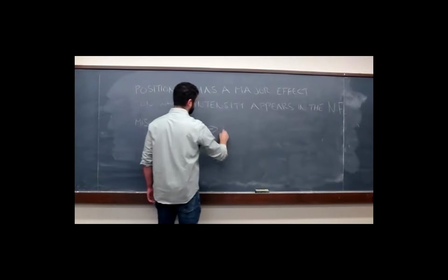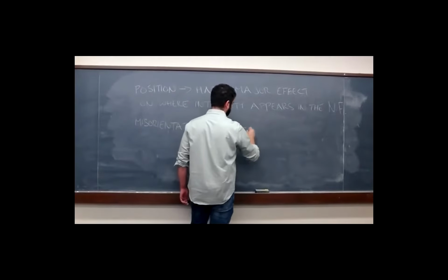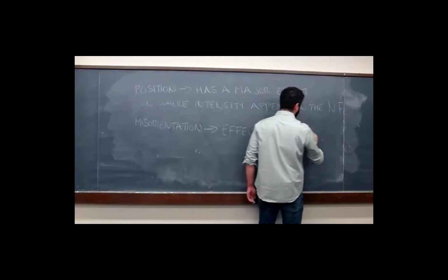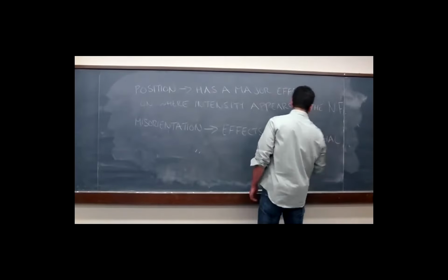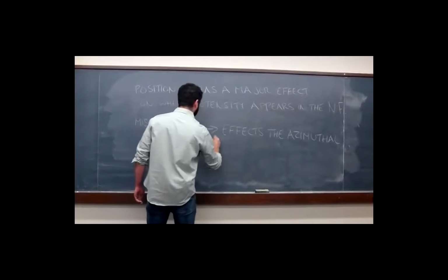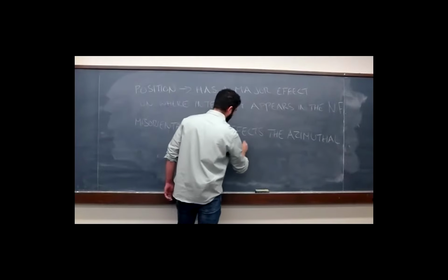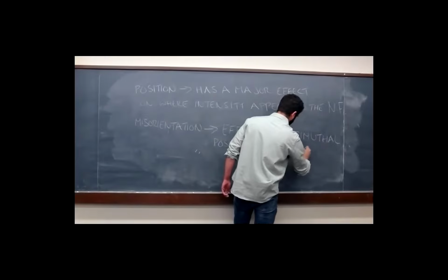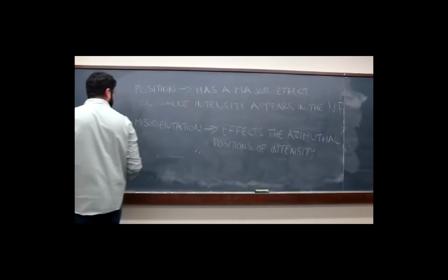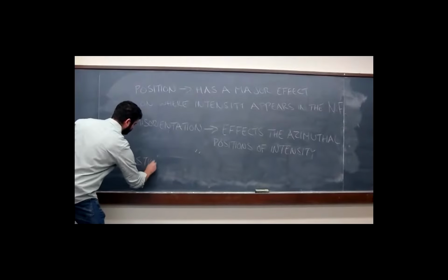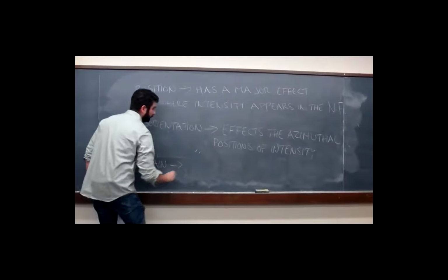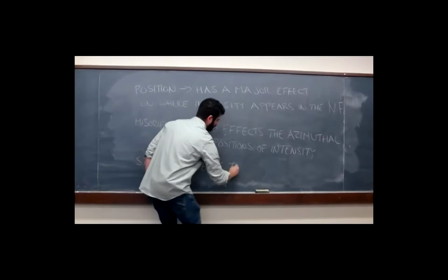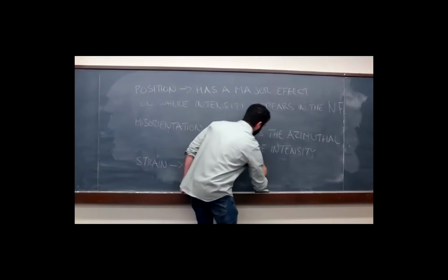Misorientation affects the azimuthal positions of intensity. Strain affects the radial positions of intensity.